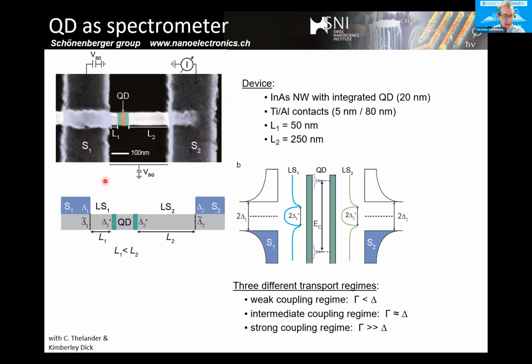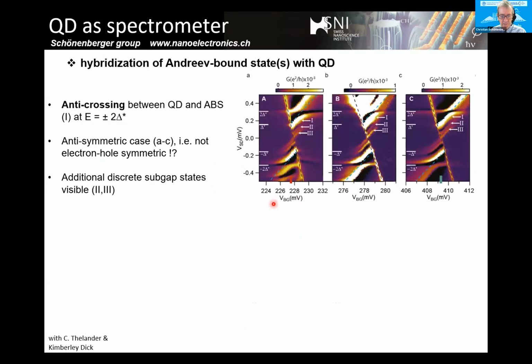So this is one which now has two superconductors, one on the left and one on the right. Again, the quantum dot is positioned asymmetrically, so there's a short lead on the left and a long lead on the right. But now it's S-dot-S. Again, we will look at how the superconductivity is induced in these two sections. Let's start at low gate voltage first, which is lower carrier density, and that's how the spectrum looks. There are 3 experiments a bit higher up in gate voltage, but that's essentially how the picture looks when you are close to the degeneracy point, the resonance state of the quantum dot.